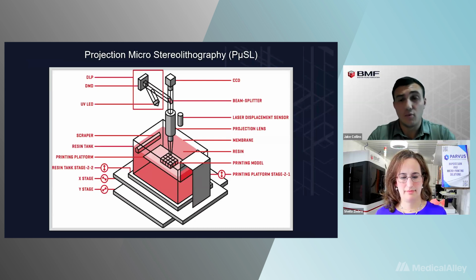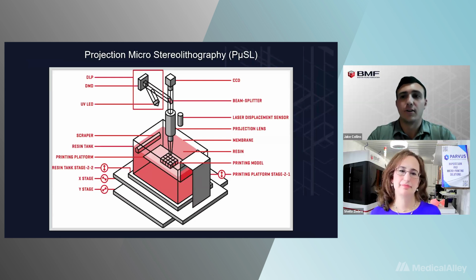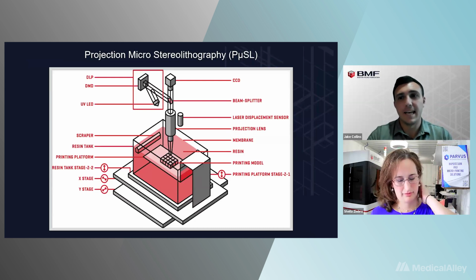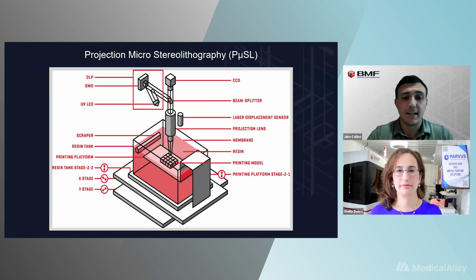And then you'll typically see resolution that's the best in the center of that build, just because of the way the projector comes down. And this is typically an issue when you're looking at really high accuracy parts, because as you move towards the edges of your build area, you get something that we call pixel pitch. It's coming down at an angle is the way that pixel is projecting. So if you say you have a 10 micron pixel, which is typically what we're talking about here with our S240 system, in traditional DLP, you might have that perfect 10 micron pixel right in the center.